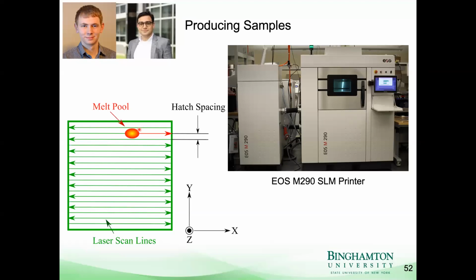But there's been very little work in the literature on how the thermal properties of metal printed parts change with print processing. When we print with our machine, we can tell it how much laser power to use, and we can also tell it how fast to move that laser over the part. Typically we operate at 200 to 400 watts, and the laser moves at maybe 1 meter per second for typical metals, on that order of magnitude. So one of the things we want to look at is how the melting process parameters change the thermal properties of different metals.